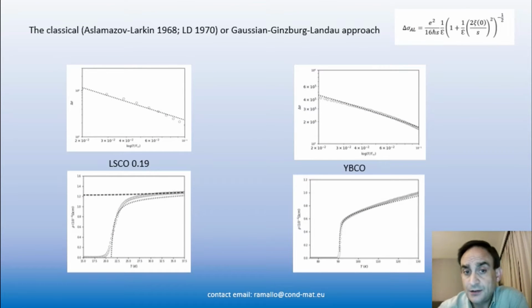So to understand these effects, the most classical framework is based on the Aslamazov-Larkin work in the late 60s and the Lawrence-Doniach generalization to layered superconductors that produced this very well-known expression that you can obtain on the basis of the Ginzburg-Landau approach with small Gaussian fluctuations. And as you see in these two figures, the agreement is quite good in a certain temperature range that comprises reduced temperatures from 0.02 to 0.1. So these figures are well known.